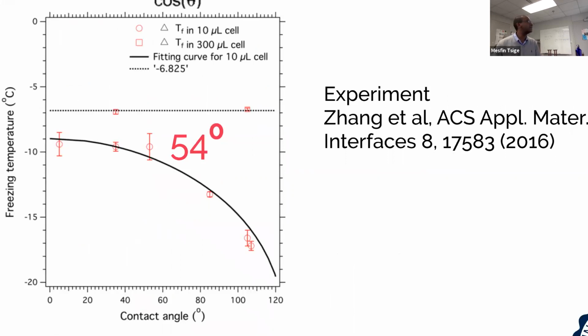On the experimental side, my collaborator Ali Dhinojwala from our department used a sum frequency generation approach, where they monitored the freezing temperature change as a function of contact angle. They considered different kinds of surfaces, sapphire and self-assembled monolayers. What they observed is that there is a change above 54 degrees of contact angle. In their case, above 54 degrees, a strong sum frequency generation peak associated with highly coordinated water seems to be forming. So highly coordinated water, that's key. Something is going on at the molecular scale.